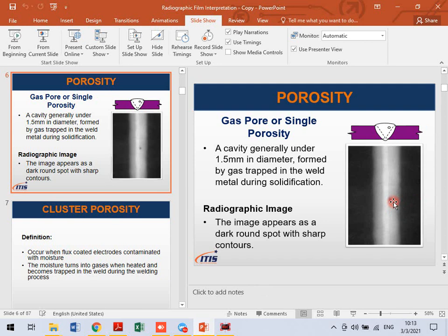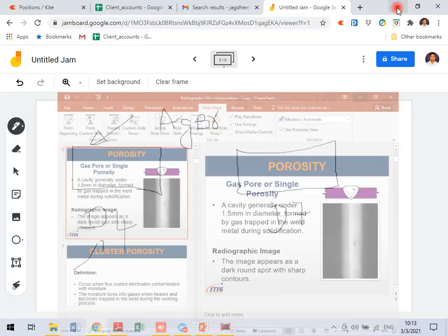So the image formed on the film is due to what? This is the first question you should answer in your mind. When you see the film, for example, when I see this image, is it due to differential absorption or not? In film, you will find a lot of images not due to differential absorption. Maybe your developer is a problem, your fixer is a problem, your hanging is a problem, your washing is wrong, anything, right? So this is more important. To understand that, you should know what this is.